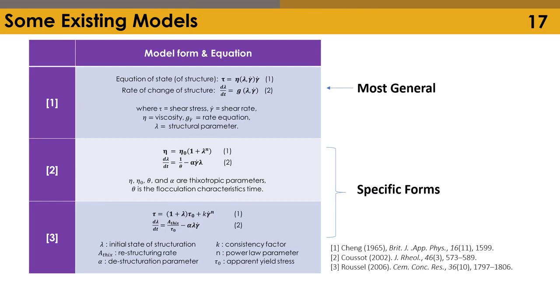So our ambition is actually to model this somehow. So we took a look at the broad literature, and there are many, many models in the literature, but we've latched on to one particular strategy wherein you start with a constitutive equation that relates shear stress to the shear rate and some sort of viscosity or viscosity-related parameter. But you modify that constitutive relationship by saying there's some form of structuration which can either form kinetically or be decomposed kinetically as a function of shear rate.